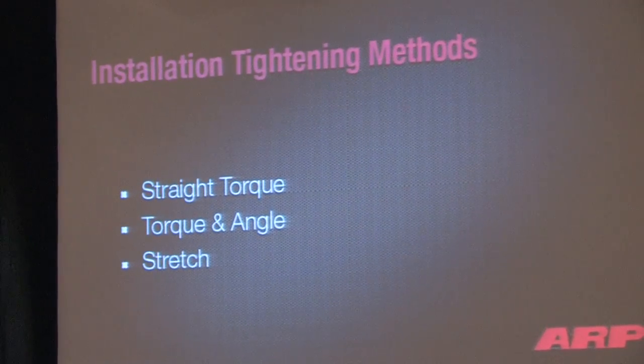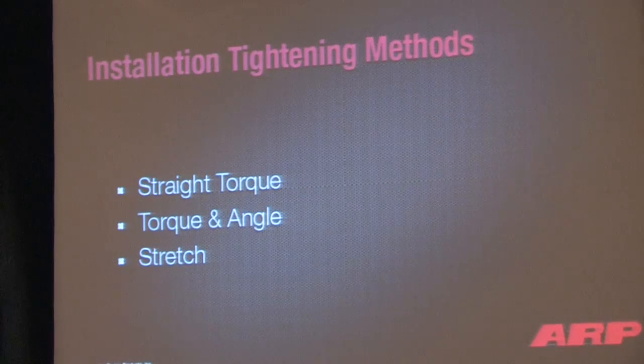Torque and angle can be used even in a situation where you're going to reuse the fastener. You just have to be aware of where the yield point is. You don't have to take it into yield to make it work. Torque and angle is a step forward in accuracy from straight torque, because with straight torque you're just concerned about friction. You're estimating what the frictional resistance is going to be to achieve a certain amount of stretch. That's mostly affected by the lubricant you're using, but also the surface finish of the surfaces where you're generating friction, in the threads and on the spot face of whatever you're working on.